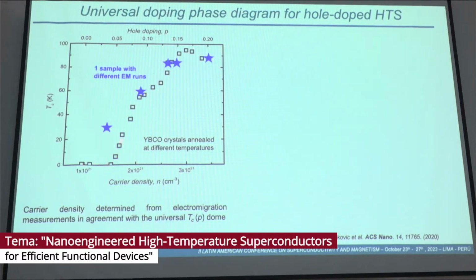And if we put all this data together in a TC versus carrier density phase graph, the squares are data that have been taken from bulk systems that have been oxygenated in different states, and the stars are different points that have been obtained by the electromigration runs. And what we can observe here is that we can go through the phase through different oxygen states in the system. And what's interesting here is that this can be done in a single sample. We don't need to, as in this work here, use many different samples oxygenated at different states. And in our case, by starting with a well-oxygenated sample, we are able to go to different states by just applying the current in the system.